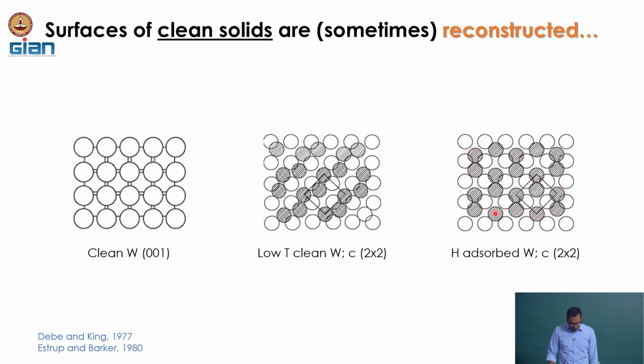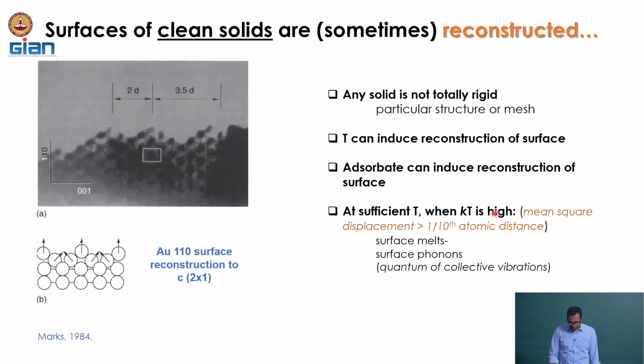Okay. That means we have two things here. Number one, the temperature can induce the restructuring of the surface. Number two, the adsorbate can induce the restructuring of the surface. And the bottom line is, any solid which is typically considered rigid is actually not rigid. Because of the temperature and the presence of adsorbate, the surface phase can change. And here I am showing another example, and this is for the gold 110 surface, and as we are seeing, the surface is not present in the 110 form, but rather it is a c(2x1) type of geometry.